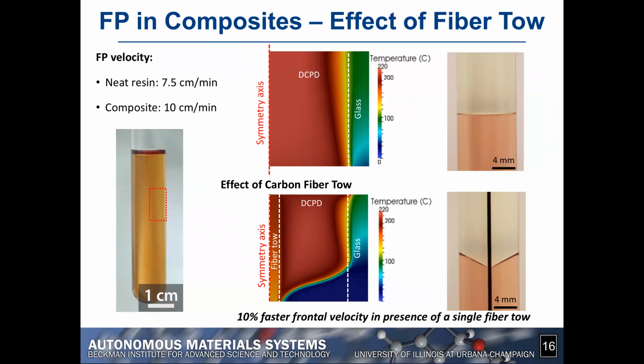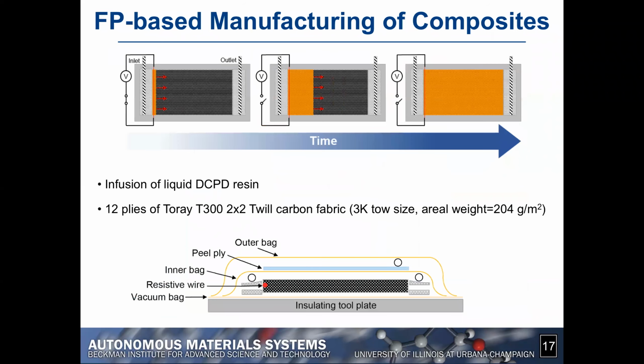So obviously the next step was to apply this kind of technology of frontal polymerization in the manufacture of composites. And here's the way we've actually done this, right? We first infuse the carbon fabric with liquid DCPD resin using a classical VARTM type of approach, vacuum-assisted resin transfer molding.